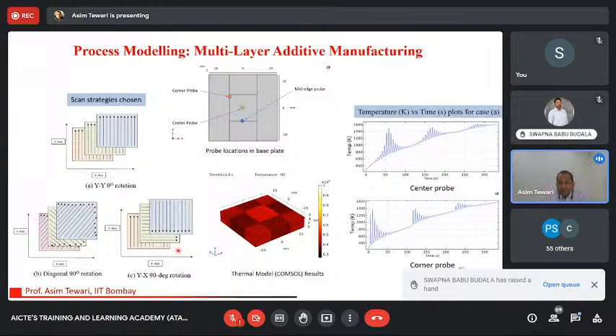So you could have many different build strategies, all generated in the computer. And this is what we are doing right now. So we are adding layer by layer material based on our build strategy, based on our power, based on our velocity and all those things. And we are seeing how is the temperature varying and how is the residual stress varying. So this is something which needs to be done before you actually start building the models in your machines. And the reason is that in the machine, it's number one, very expensive to do that. Number two, in the machine, you don't have a way to measure residual stresses right away. And because they are internal parts, that's when it can lead to distortions and cracks internally, but you won't be able to measure those quantities which you could do in these simulations.